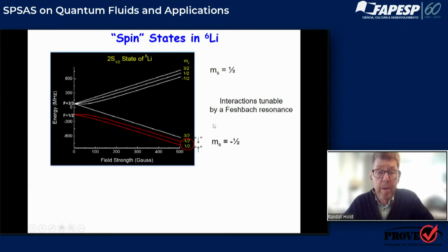So in our experiment, we used two spin states of lithium-6 to be the stand-ins for the two different up and down spins of the electrons in a real electronic material. And these two levels of lithium-6 have a very nice Feshbach resonance in which the interaction is tunable over a wide range. And that's very convenient and very important for these experiments.